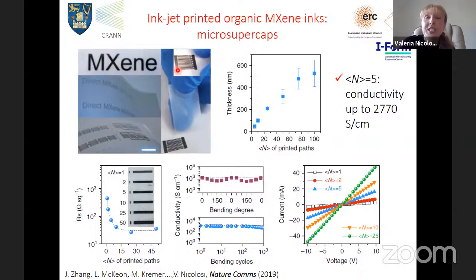Again, we love interdigitated devices because they allow us to reach higher surface and higher capacitance. Here are devices printed in series and printed in parallel, so it shows you the versatility of this very, very fast way of making devices. And we could see that, of course, the more layers we were printing, the higher the thickness was getting, and the more conductive our device was getting. Here is how the resistivity drops with the number of layers. Already printing 5 layers, we could reach a conductivity of about 2,700 Siemens per centimeter, which is really high.